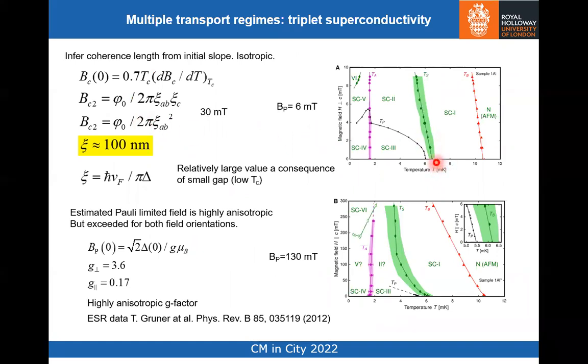If we look at the initial slope of the depression of the superconducting transition temperature, then using conventional theory for that slope, we can infer an upper critical field of about 30 millitesla, and that gives you a coherence length of order 100 nanometers, which is relatively isotropic. And that large value of the coherence length, despite the fact that we're in a heavy fermion system, so the Fermi velocity is relatively low, and of course the transition is happening at a low temperature, so the gap is small, that combination can give you this relatively large coherence length.